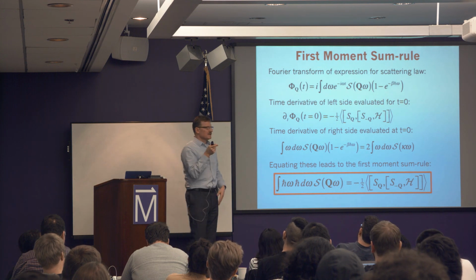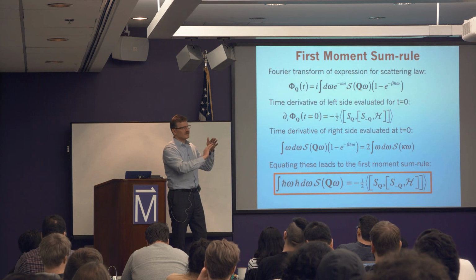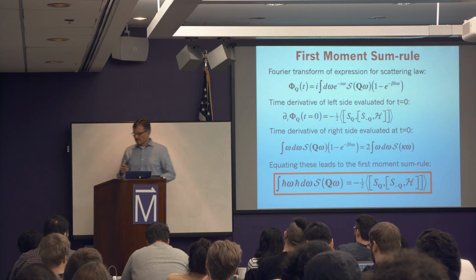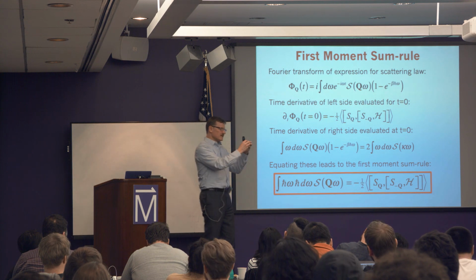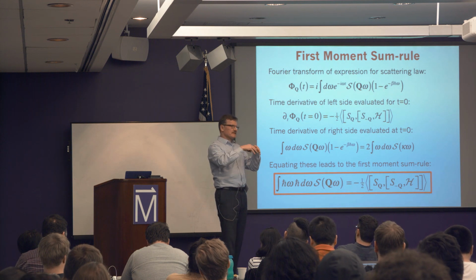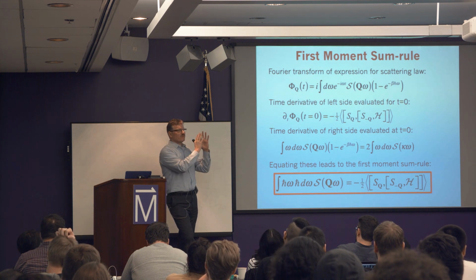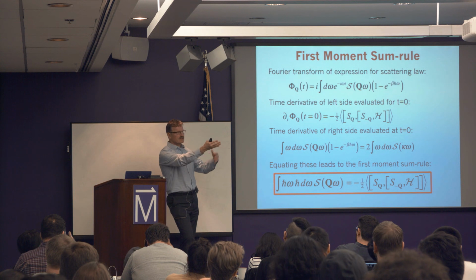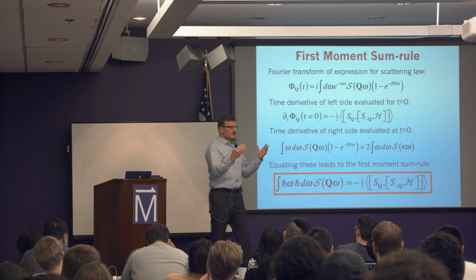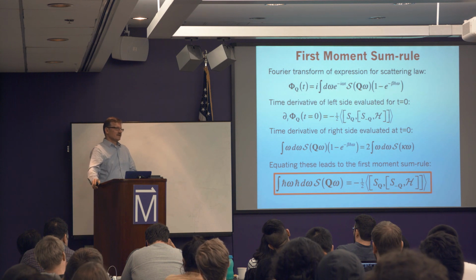When that happens, what I call the form factor comes into play, and it will cut off. The dipole moment which is leaked out onto the oxygen atoms will be much harder to see because it sits in a more distributed orbital, and therefore it only contributes to scattering at very, very low wave vector transfer. So it is in fact as if you lose overall spectral density by this process. It's as if you just have less copper in there, or less of your 3D transition metal.